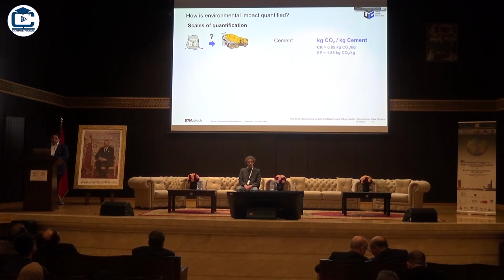It's important when we are talking about CO2 to have a look at how the environmental impact of this material is quantified. A very classic way of doing this is to compute the kilograms of CO2 per kilograms of cement that we are using. And there are numbers here that are very well known to you. For example, clinker 0.85, classic reference numbers, superplasticizer 1.88.